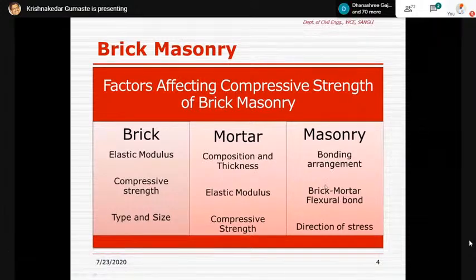The other criterion is the brick mortar flexural bond. The strength of the brick and the strength of the mortar are important, but let us take an imaginary situation. The mortar is also very, very strong. In that case, in terms of the kind of stresses that are occurring in the wall, depending on whether it is only axially loaded or laterally loaded, the flexural bond or the interface bond between the brick and the mortar also plays a very important role in deciding the brick masonry strength. In fact, the brick and the mortar may not fail, but the interface between the brick and the mortar may sometimes fail and may lead to the failure of the masonry itself. These are some kinds of studies which we also look at.